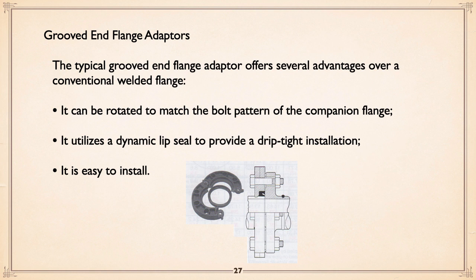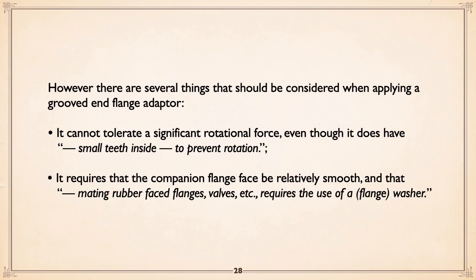We're showing grooved end flange adapters again, and they have the advantages. They can be rotated, they have a dynamic lip seal, drip tight, and they're very easy to install. And again, as we suggest, they can't tolerate significant rotational force, like if you've got a T with a valve in one end. We had this happen once. That's enough rotational force that it actually rotated the thing down. And it requires that what you're bolting up against be suitable. Rubber-faced flanges, valves, etc. require use of a flange washer, which is basically nothing but a chunk of steel, like a big washer, so that the valve, let's say you've got a valve that either has a rough surface or something, but rubber-faced, is going against the washer, and on the other side, the Victaulic flange adapter is going against that nice smooth washer.